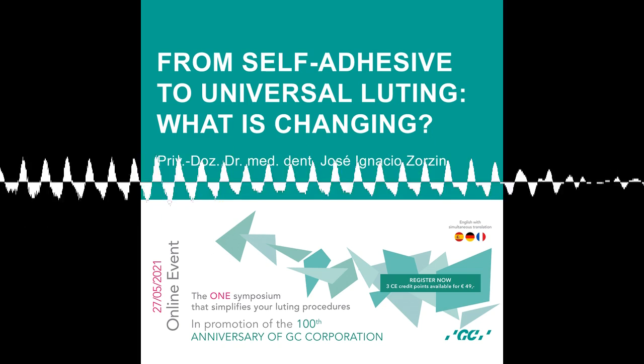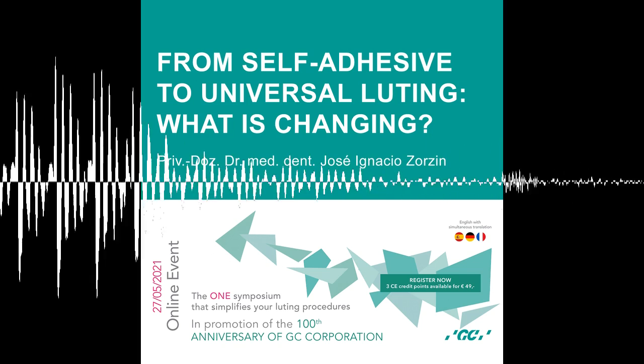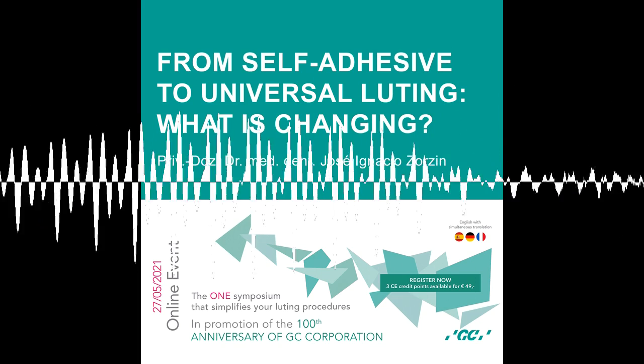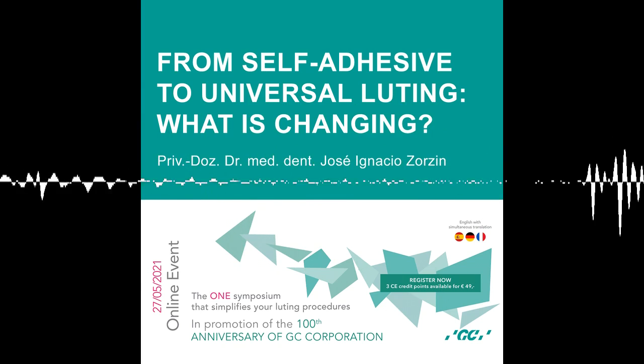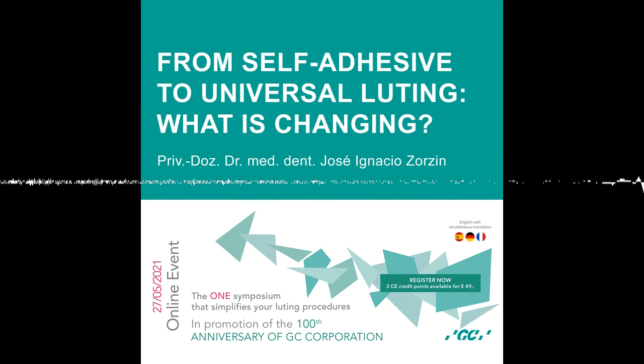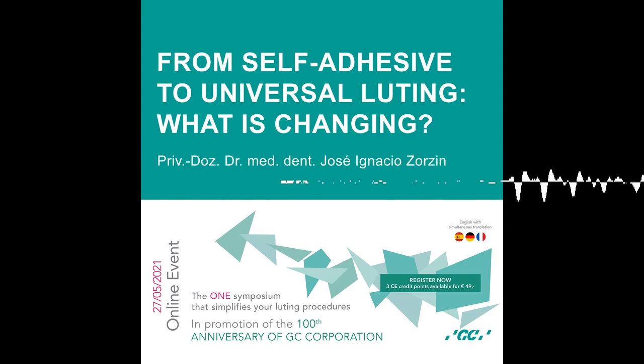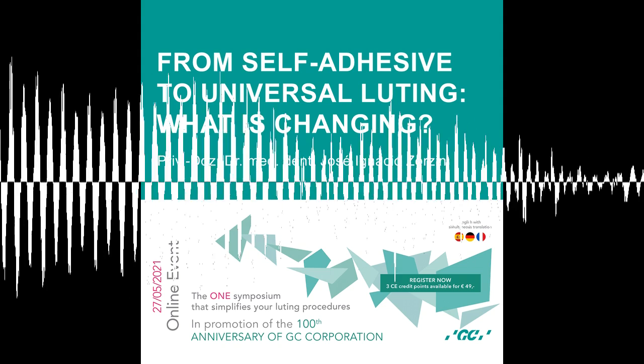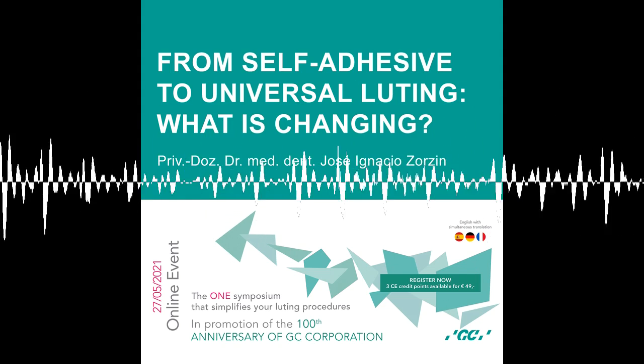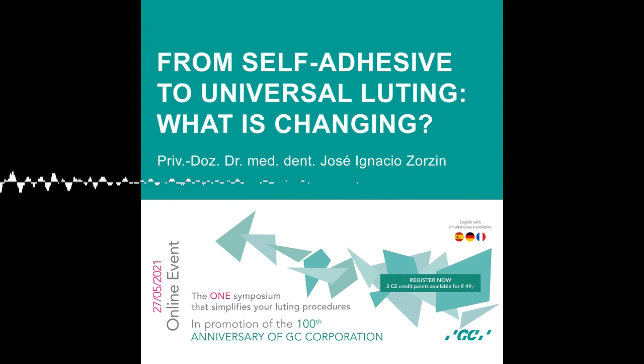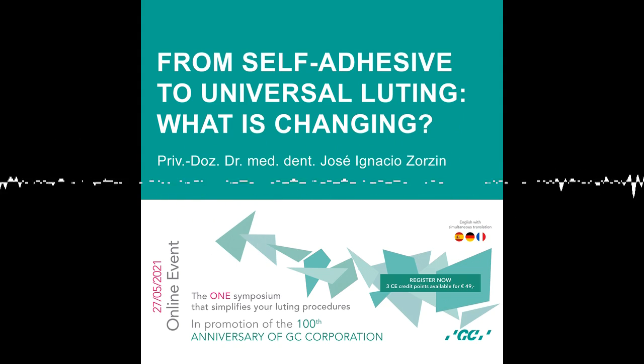Is the heat generation really a problem? First, it feels not comfortable. If you don't have anesthesia and you have a vital tooth under it, you will feel the curing unit, and it's very uncomfortable. The way we do light curing actually with the lamps we have, I think heat is something we have to keep in mind, but we don't have to overestimate this problem at all. Mainly, when we're doing indirect restorations, we are also dealing a lot with teeth which are not vital anymore, which have a root canal treatment. So this aspect would not be that important when we have non-vital teeth. So I try to light cure whenever possible.